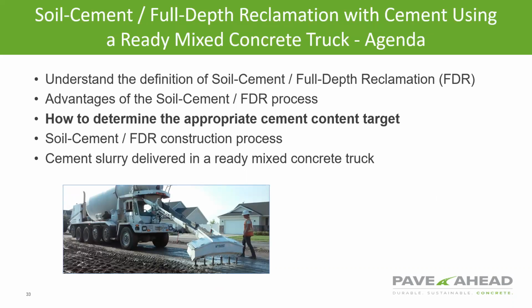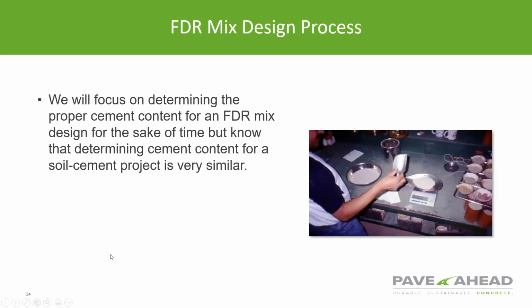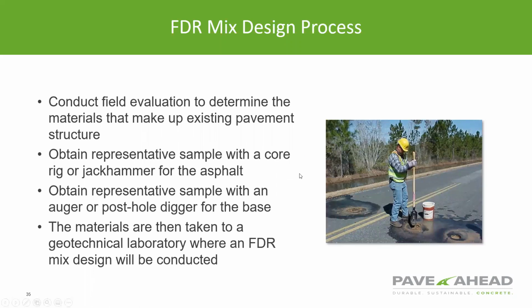Next topic that I'd like to cover is how to determine the appropriate cement content. And we're going to focus on FDR for the sake of time, but the same provisions really apply for soil cement and the other family of cement products that you saw earlier. And the basic process is you conduct a field evaluation to determine the materials that are going to make up the existing pavement. So we want to take those materials from the field, bring them back to the lab, and combine them in that same proportion that you find them in the field. And you can obtain a representative sample with a core rig or jackhammer for the asphalt, auger or post hole digger for the base below. And then materials are taken back to the lab and recombined.